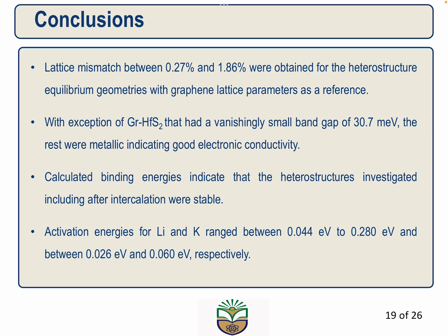electrons easily. Then the other thing that we also considered was the binding energies of the heterostructures, including after intercalation, and in all the cases we were able to show that the binding energies were negative, an indication that even after intercalation our system remained thermodynamically stable.